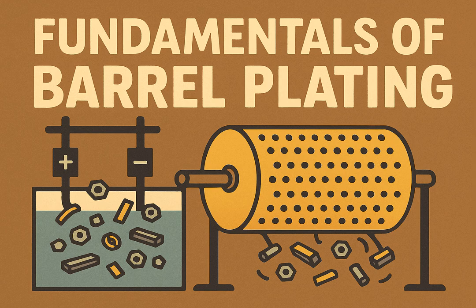Why would that happen? This is most likely caused by current interruptions during the plating cycle. In a barrel, the flexible danglers might occasionally lift out of the tumbling load, or there could be loose electrical contacts in the barrel's hanger assembly. Even a brief break in current can cause a thin, passive layer to form on the part surface. So the plating stops, then starts again on a slightly oxidized surface. Exactly. When the current resumes, a new layer plates on top of the passive one, creating a weak interface that can delaminate, appearing as a double layer. This is especially problematic in low current density areas of the barrel where contact might be less consistent.